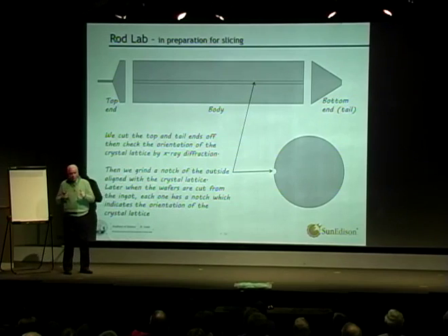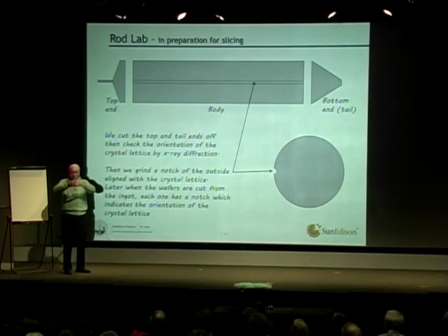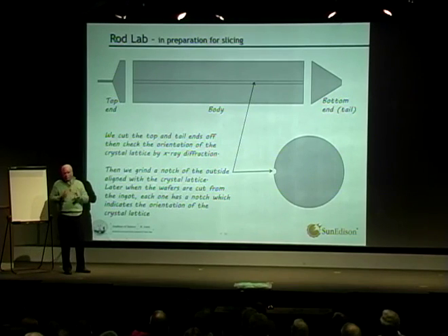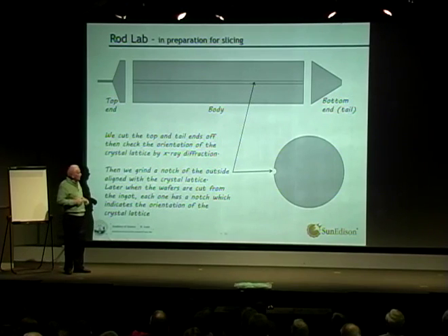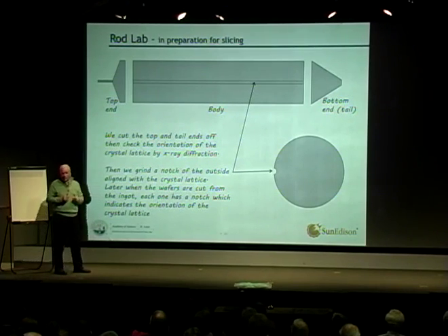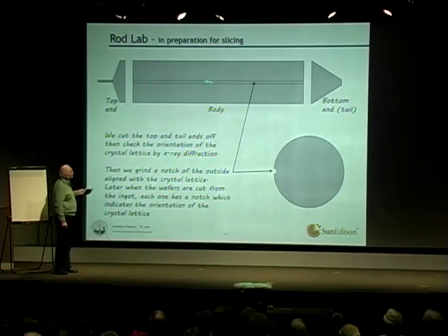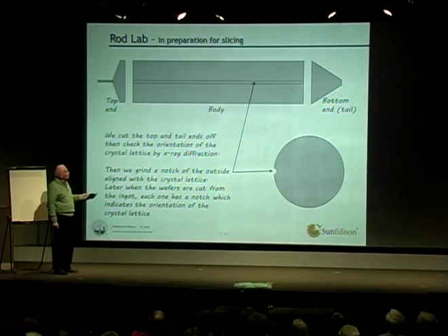Now, the other thing that's important about silicon, because this is a single crystal and all the atoms line up, we want to know what direction are those atoms in. Are they like this, like this, or like this? We need to understand that so that when we build the integrated circuit, everything's in the right direction. And so what we do is we use X-rays to determine the orientation of this body. And then when we know the orientation, we mark it, and then we grind a notch all the way along it. In cross-section, it looks like this with a little notch.